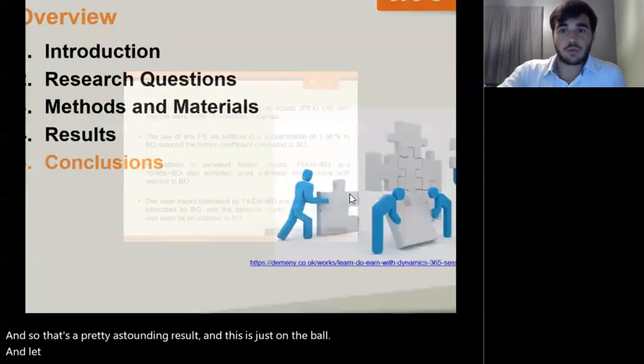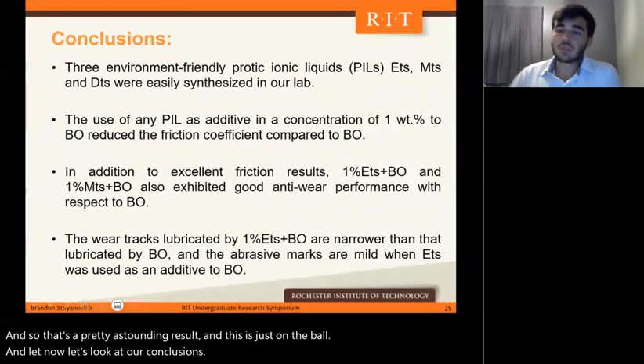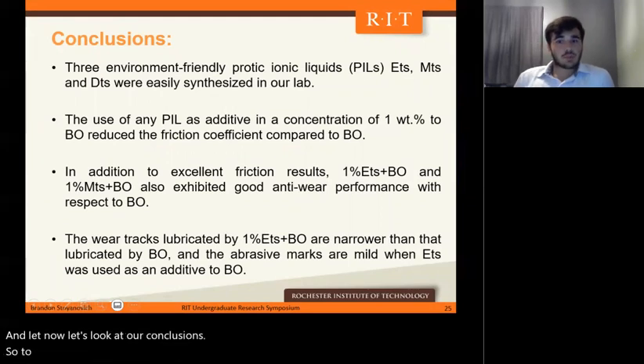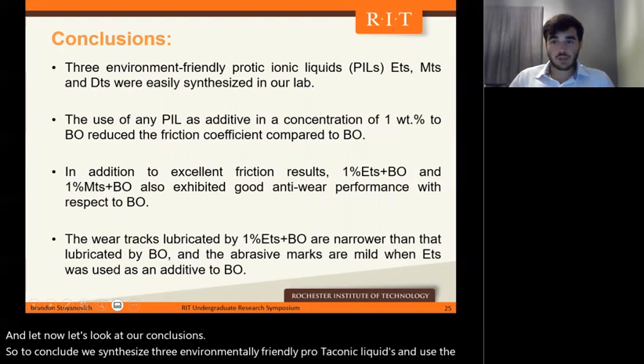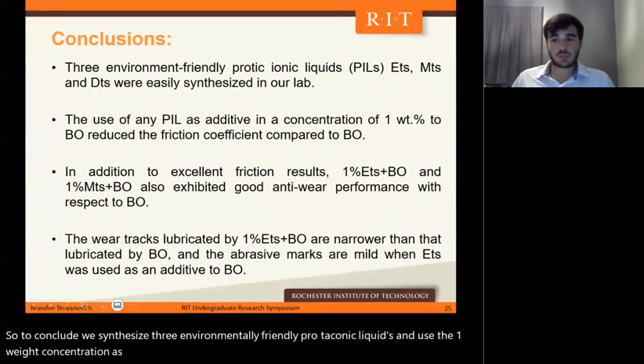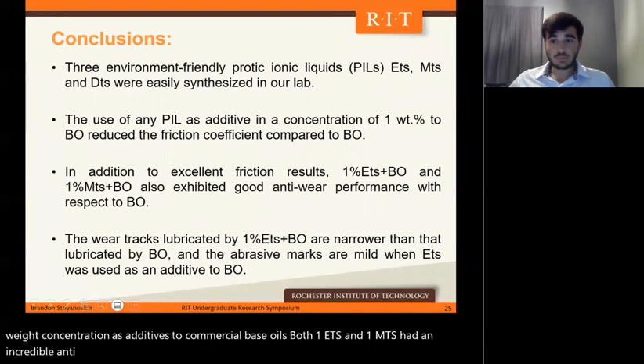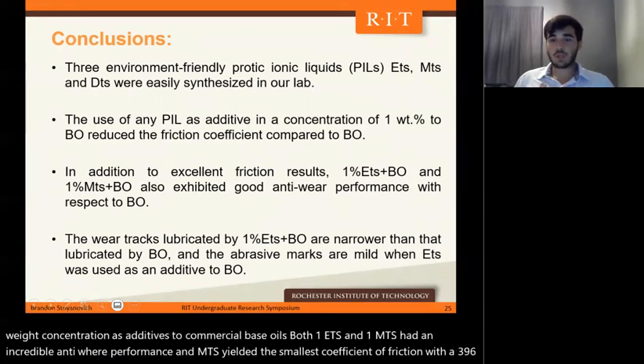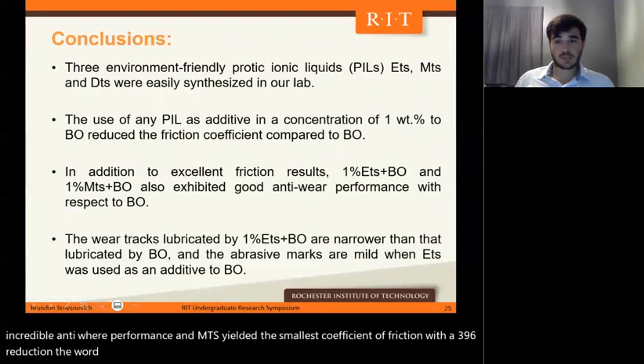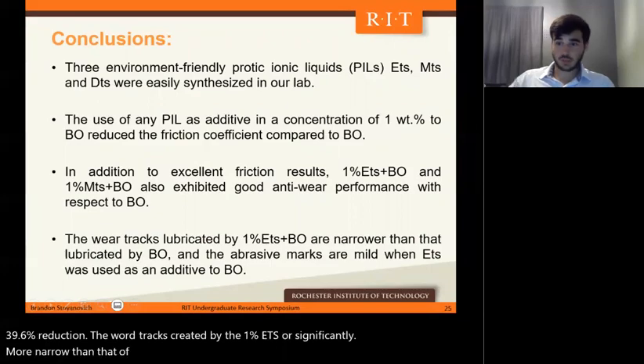Now let's look at our conclusions. So to conclude, we synthesized 3 environmentally friendly Protic Ionic Liquids and used a 1% weight concentration as additives to commercial base oils. Both 1% ETS and 1% MTS had an incredible anti-wear performance. And MTS yielded the smallest coefficient of friction with a 39.6% reduction. The wear tracks created by the 1% ETS were significantly more narrow than that of commercial base oils, which leads us to wondering